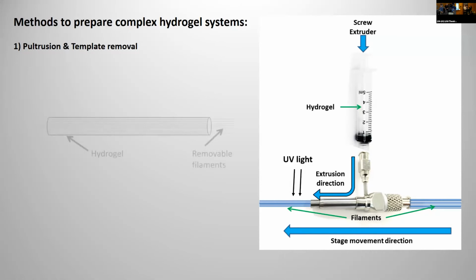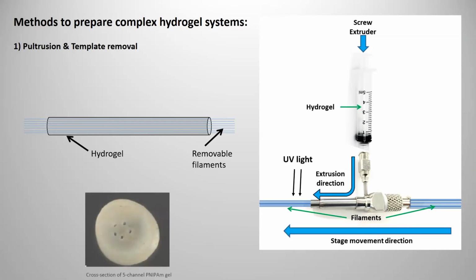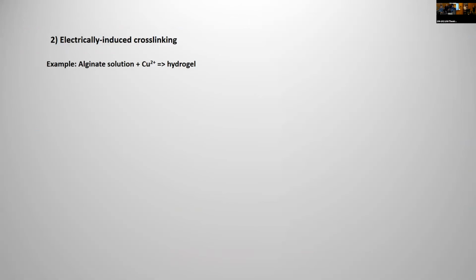So what you should get at the end looks something like this. Your hydrogel is extruded around in a continuous fashion, these long fibers that go all the way through the middle. And then we can remove them, and a cross section there at the bottom just shows the kind of end result. So you can get a nice channeled gel with these holes in it. You can then fill those holes with whatever you want or leave them hollow, depends on the application. You could have electrically conducting fibers stuck in there that you can stimulate your material directly, or you could use it to flow different liquids through the middle that are going to do something functional. So that was the very first thing I actually did during this fellowship.